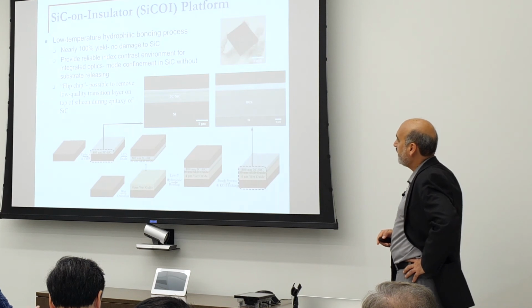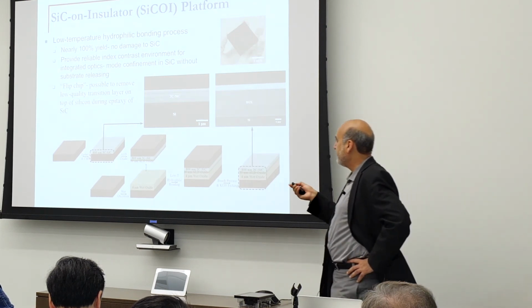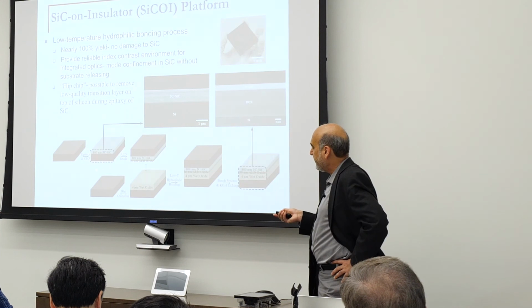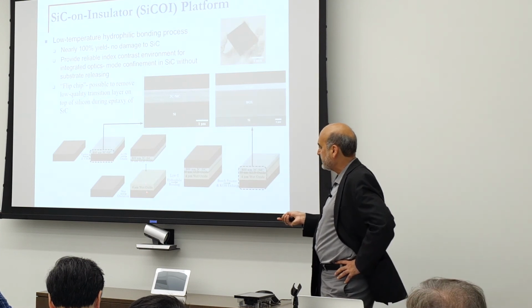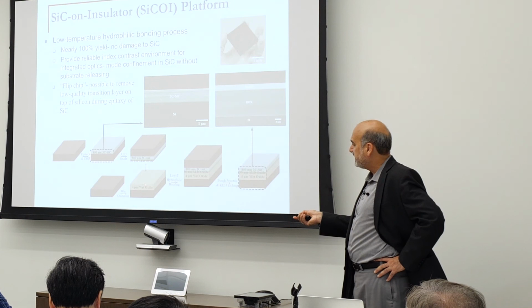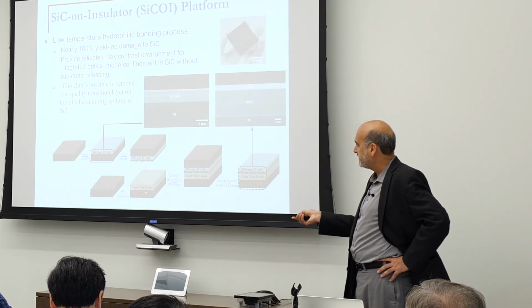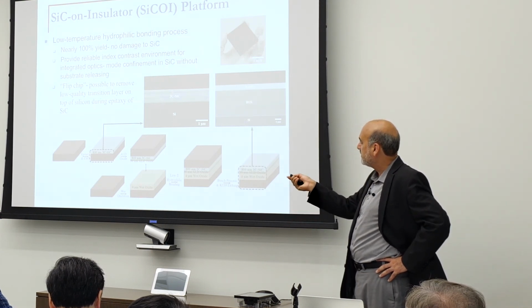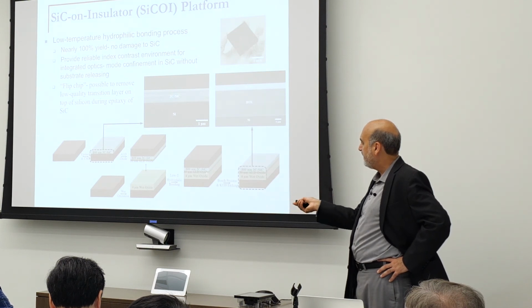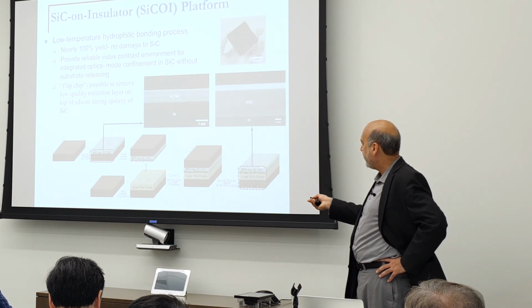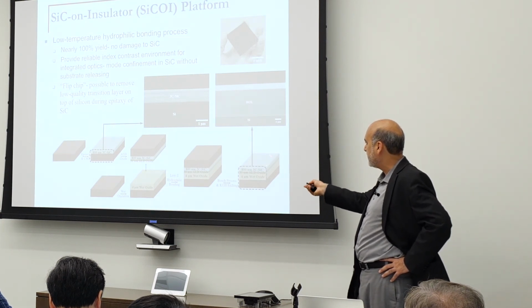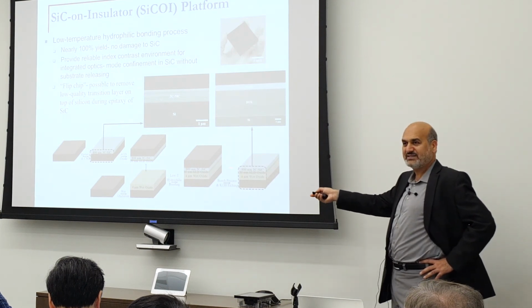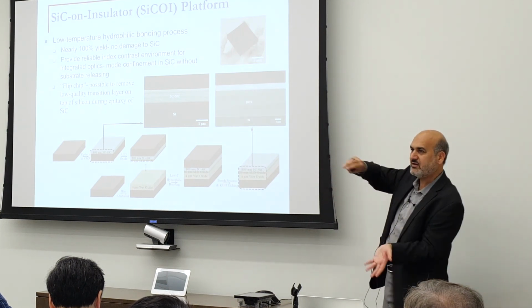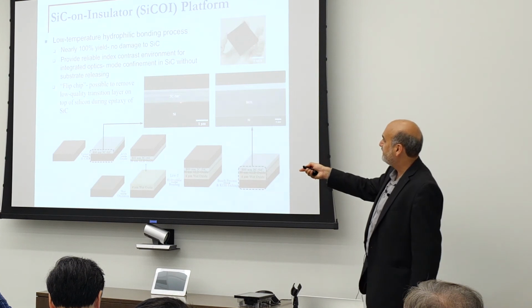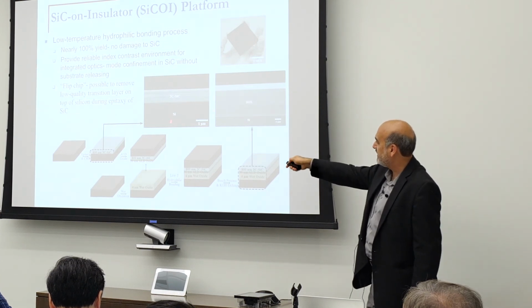So what we work with is a bonding process where technically we grow a layer of oxide that is thick enough that doesn't let light see the silicon underneath, and then we bond this silicon carbide on silicon on top of my oxide. By removing silicon by etching, I get access to the top layer, which is the culprit in a lot of experiments. That's the very low quality. So I kind of reverse this material and then get rid of silicon.